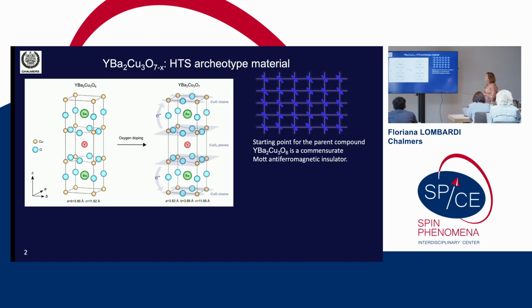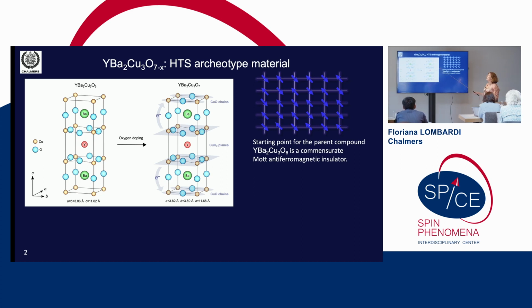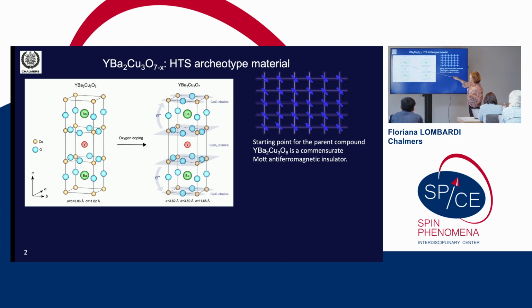Okay, so briefly, the archetypal HTC superconductor is YBCO. Why it has been studied so extensively is because it can be quite easily grown into films. So you have three perovskite cells, one on top of each other, and the parent compound is a Mott insulator. And by adding oxygen in what are called the chains, one can induce superconductivity.